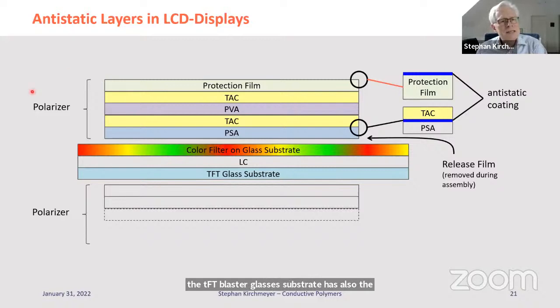On the sides, we always have a polarizer into two areas, into, let's say, two directions. And the polarizer is specifically needed for the LCD display to make the LC effect. The polarizer consists of the PVA, which is a very soft polymer containing the iodine. The iodine is then used as, let's say, the polarizer itself, because iodine penetrates very, very efficiently into the environment. It needs to be sealed by something, and this is the so-called TAC film.